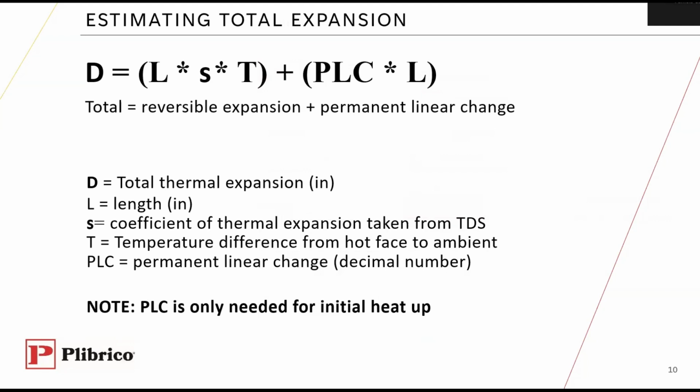And then now, in the case that you're dealing with pre-fired shapes, precast shapes, you don't need to worry about that permanent linear change because that's already occurred. You only need to worry about the reversible thermal expansion.